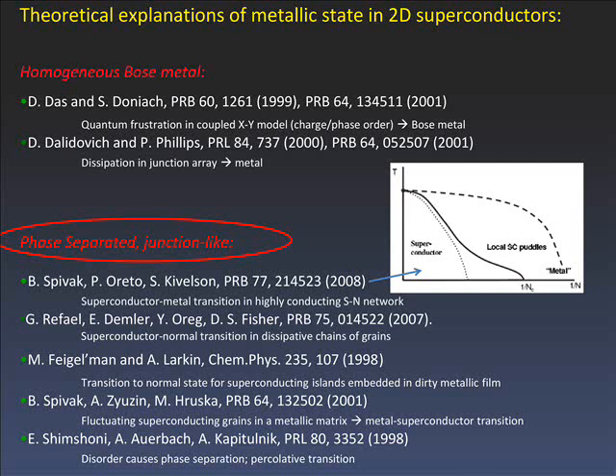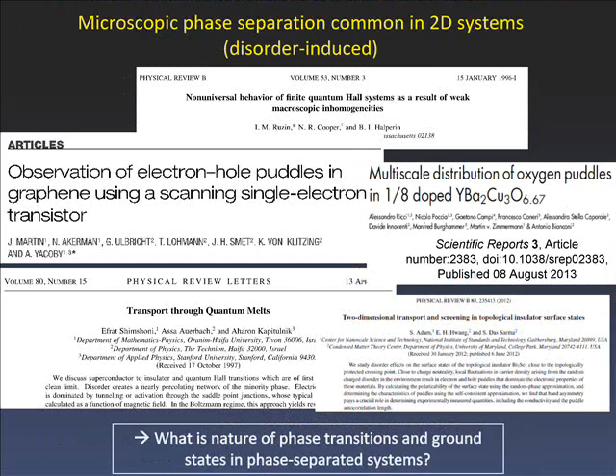There's been a lot of theoretical work trying to understand these metallic states. These days, the theory has really converged on the idea that these low-temperature metallic states are likely due to phase-separated junction-like systems — for example, little tiny islands of superconductor embedded in a metal in a highly-conducting network. This is a paper by Spivak et al., and you can see that as you make the superconducting islands further and further apart, you get a transition from a superconductor to a phase-separated system to a metal.